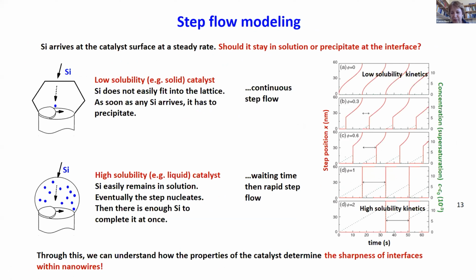So without going into a whole lot of detail, I should just point out that we have a steady supply of the growth material. So silicon arrives at the catalyst at a steady rate, and it has to decide what to do. Supposing the catalyst has very low solubility for the growth species, then the silicon comes in, it's got nowhere to go, it lands immediately, it attaches onto the growth surface, and the steps move gradually across as the nanowire grows. Instead, if there's a high solubility for the growth species in the catalyst, it will easily remain in solution, but eventually the chemical potential of dissolved silicon will rise high enough that something has to give. It has to precipitate, and at the moment it nucleates a step, enough material is present to complete the whole step all at once. So you can see that you can relate the kinetics you see in the movies to the physical parameters of the materials that are involved in the nanoscale process.